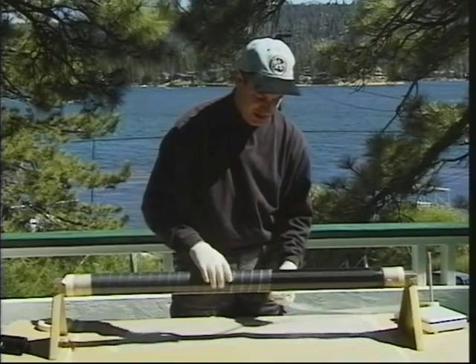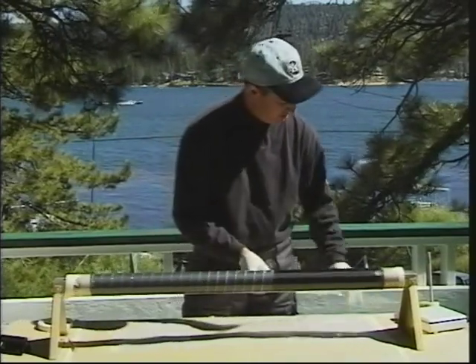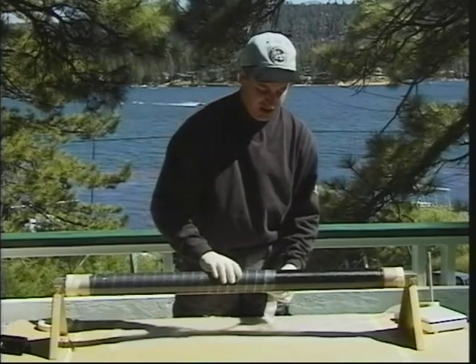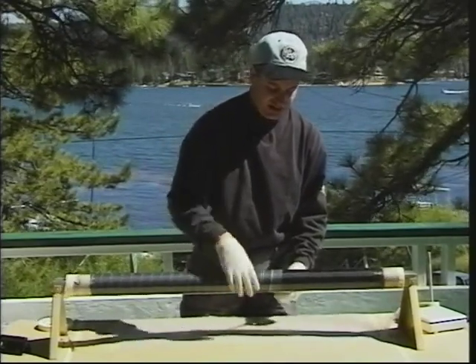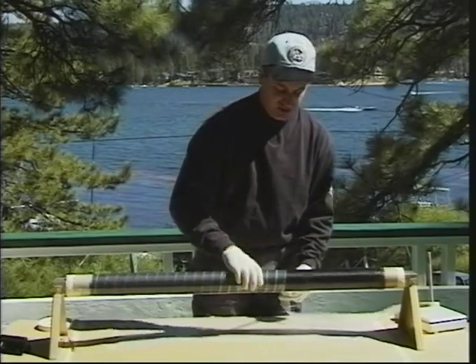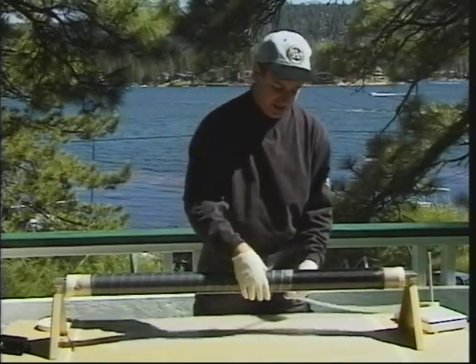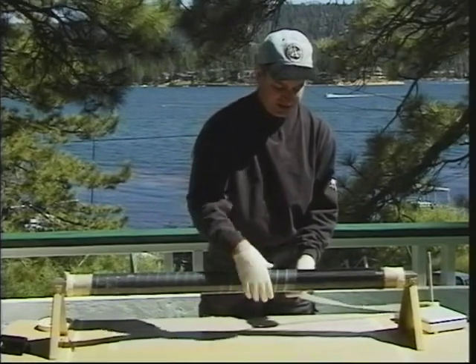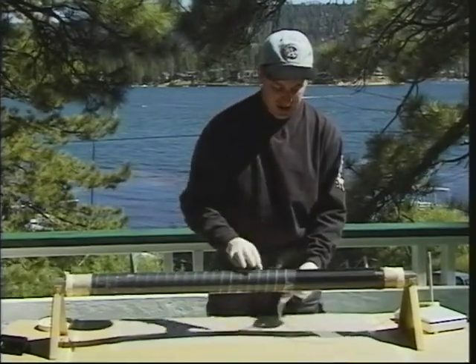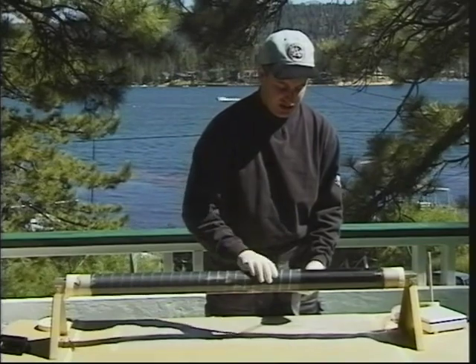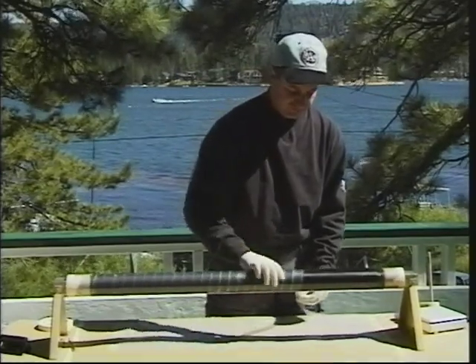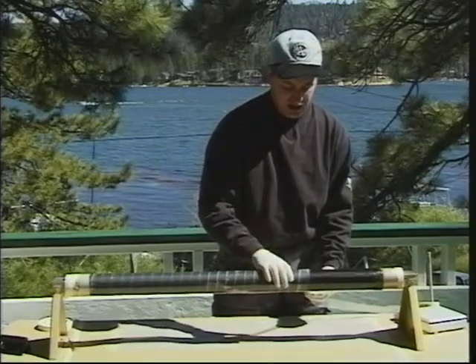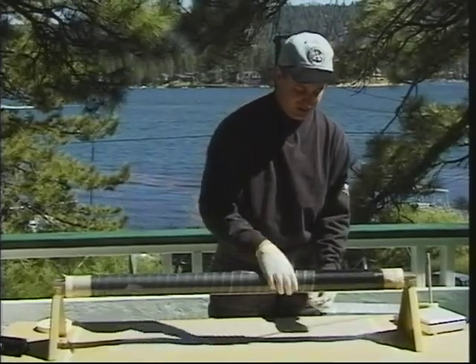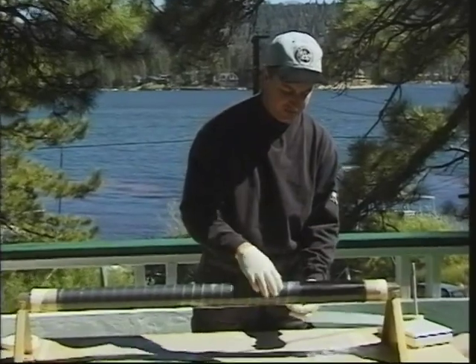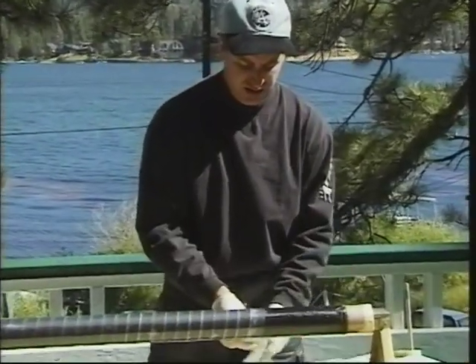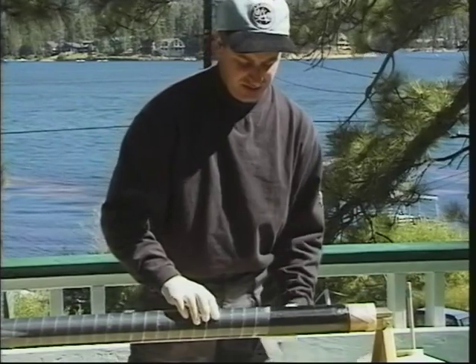Well, we're cruising pretty well now with the tape, reaching about 2/3. Believe me, compared to vacuum bagging, this stuff goes on real quick. Vacuum bagging parts like this takes a colossal amount of time in the setup and in the actual application of them to get a good result. So this is a real good way of getting a really strong, true aerospace composite structure in a quick and easy and relatively clean way.